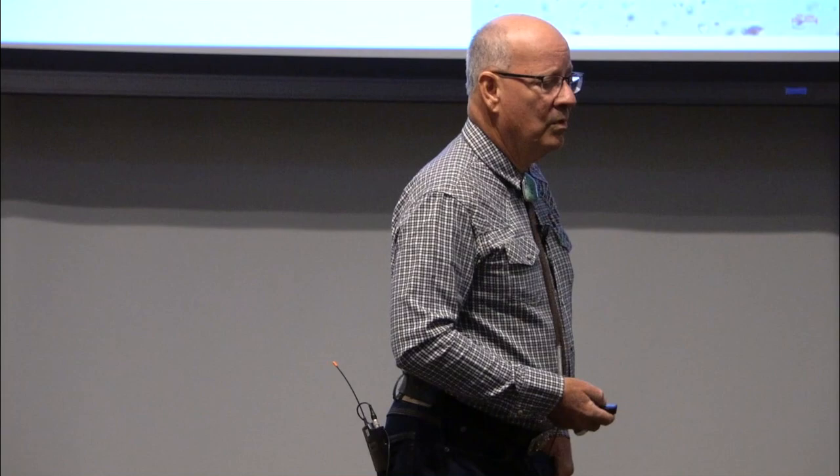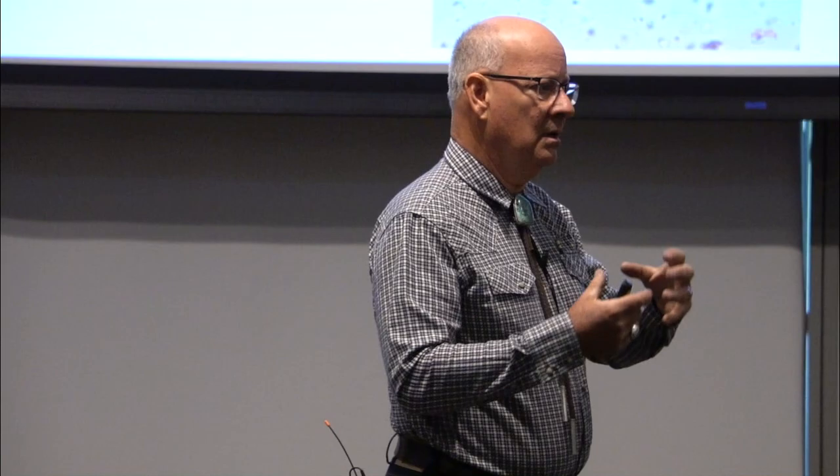At Drake and at Clarkdale we're making the same kind of material all the time. When you look at a piece of cement clinker — we call it clinker because it comes out of a big hot kiln and it rolls around like a magma, producing crystalline calcium silicates and a matrix. Those clinker grains look like this under a microscope after polishing and etching. These are the calcium silicate grains — tricalcium silicate and dicalcium silicate — with matrix in between. This was literally a magma produced by raw meal being fired up to about 1,500–1,600 degrees C. The clinkers are ground with gypsum to control set, making the Portland cement we use. We add water to set hydraulically and use chemical admixtures.